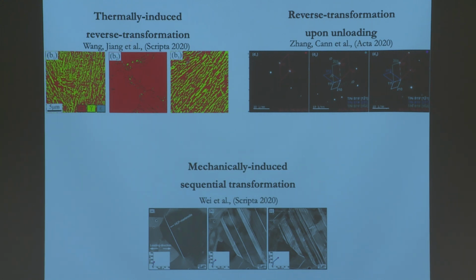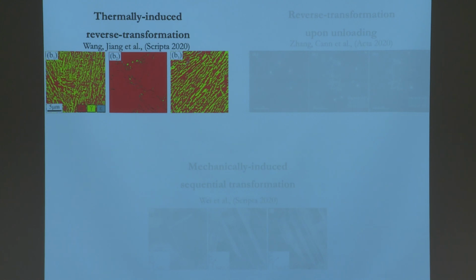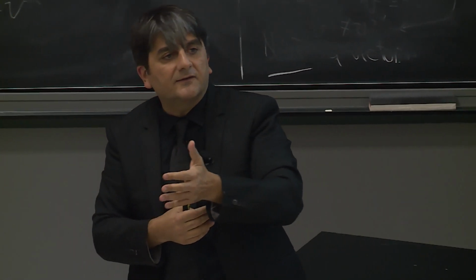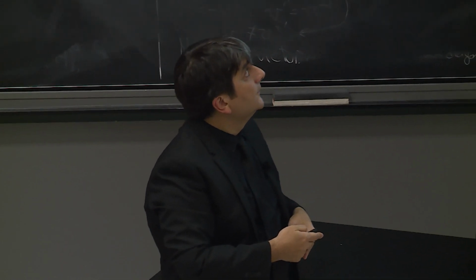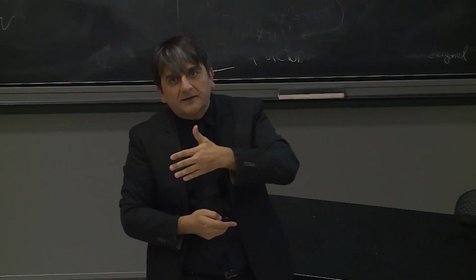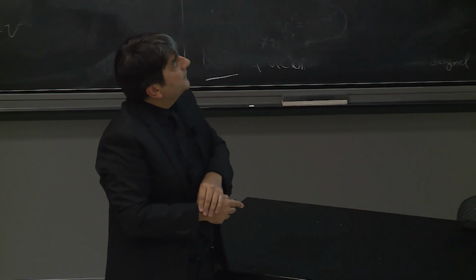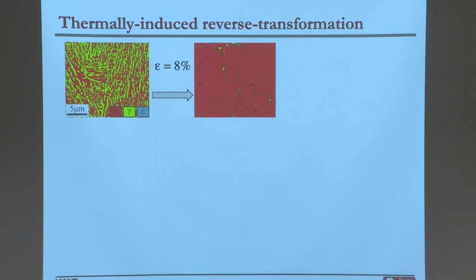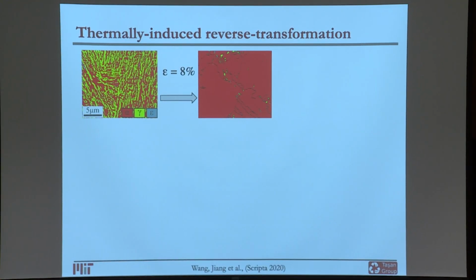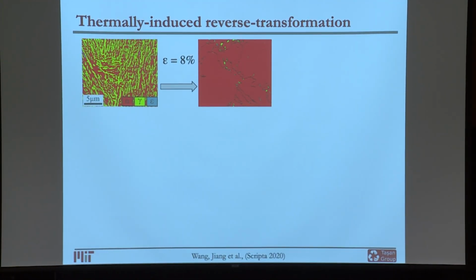So in the case of thermally induced reverse transformation, as the name implies, what you are doing is designing a microstructure in such a way that you can have the forward transformation that you want. So you deform it, there is going to be the forward transformation. But then you can apply a heat treatment. Because you designed the microstructure in a certain way, the material comes back to a state that's very similar to what it began with. So essentially, you are applying a heat treatment to revert the microstructure back to its original state. It looks like this, for instance. You start with a BCT FCC microstructure. This specific example is a medium manganese steel. You deform it 8%, so now the martensitic transformation has taken place.